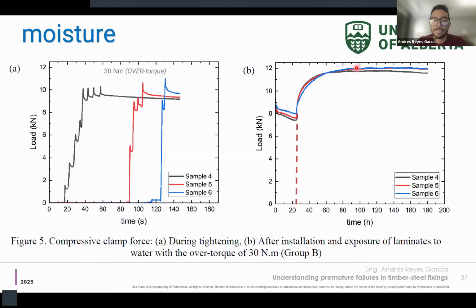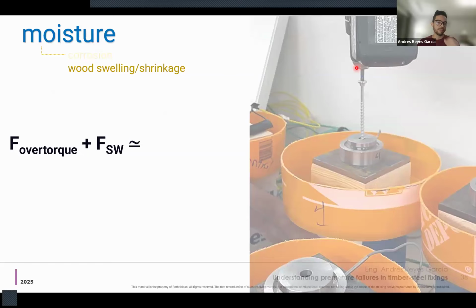So our conclusion here is that the effect of over torque, so the force given by over torque plus the force given by swelling, can get to roughly 60 to 65% of the tensile capacity of the screw, which is a lot. It's a lot for a pre-stress. We didn't get to a failure, and we don't know if only over torque or only swelling will ever lead to failure. Nonetheless, it is a very significant pre-stressor in steel, especially in thick plates to timber connection, so around 65%.